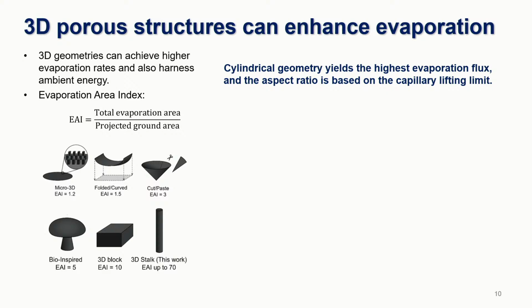So we've also looked at, instead of this two-dimensional structure, what if we work with 3D structures? So for example, adding these micro patterns on a 2D surface, or creating a cone, a cuboid, a block, or a cylinder. So in these cases, you can significantly increase your evaporation area because you have all this three-dimensional surface, but your ground area does not change.